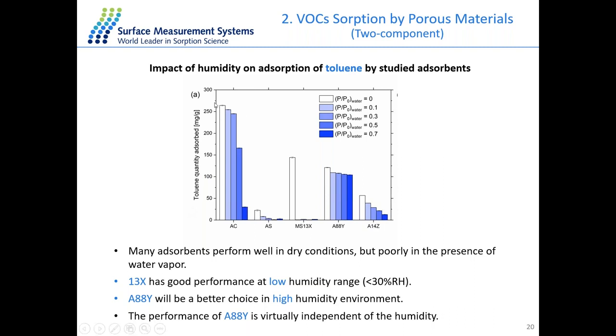In the case of the charcoal sample, on the left-hand side, at dry condition, which is the white bar here, it has the highest uptake, around 25%. This uptake is fairly the same when the humidity is below 30% RH. But if we go to higher humidity, like 70% RH, the toluene uptake will drop a lot and become 10 times smaller than the dry condition. So this data explains that to get a good VOC capture capacity when we apply charcoal as the porous material, we may need to use the charcoal only in areas with low humidity levels. Otherwise, it will not function as before.